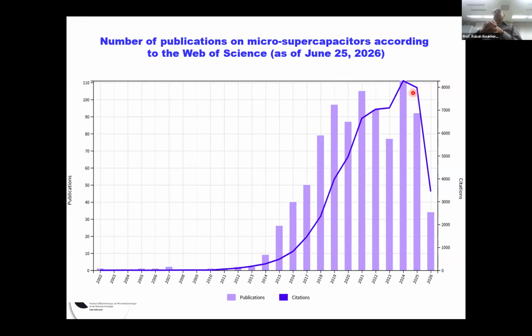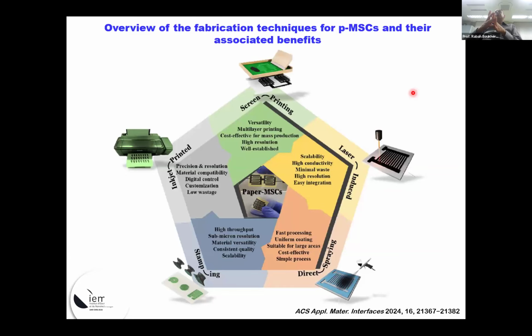It's a powder form. You make probably a few tens of milligrams, and it's enough to finalize a study to make a publication. But definitely on micro supercapacitors, it's slightly different, because you need really a different technology than just those we commonly use in the chemistry laboratory. As you can see, here are the different fabrication techniques of micro supercapacitors. You have the screen printing, you have the inkjet printing, stamping, spraying, and laser-induced technique.